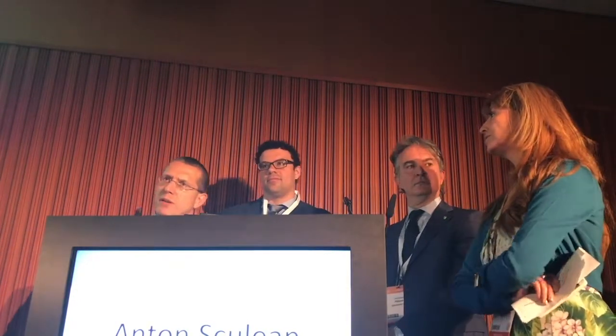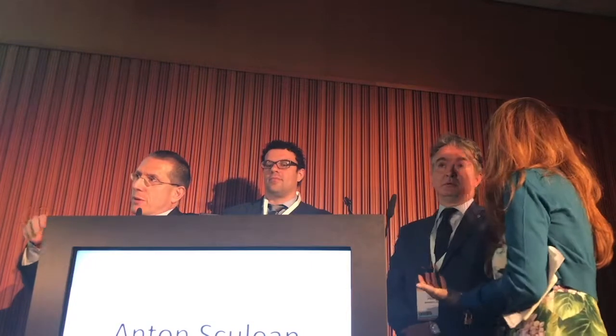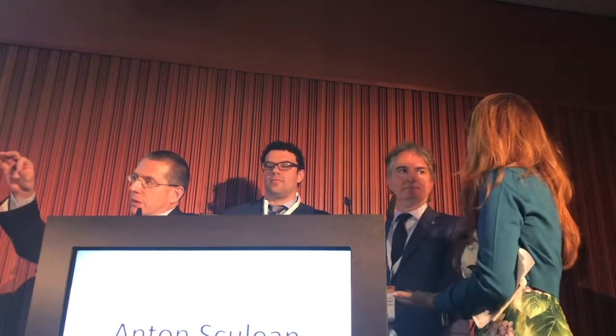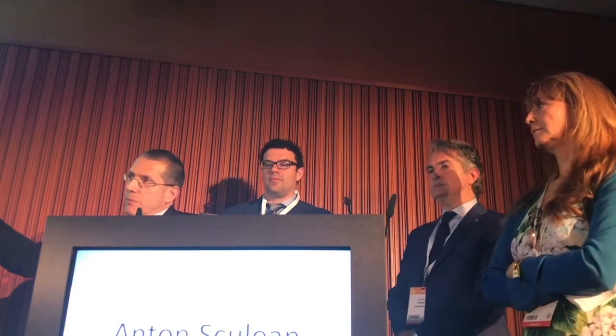We also have one very nice study conducted by Dr. Eliezer on diabetic rats, impregnating a collagen membrane with hyaluronic acid, and the degradation of the collagen membrane was slower in uncontrolled diabetic rats. I didn't present this data because I would like her to present it at the IADR, but it is a very nice study. Especially in uncontrolled diabetic animals, it was a statistically significant difference, and it was proven histologically.